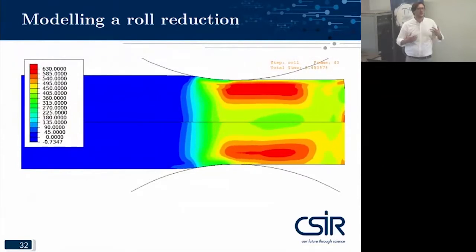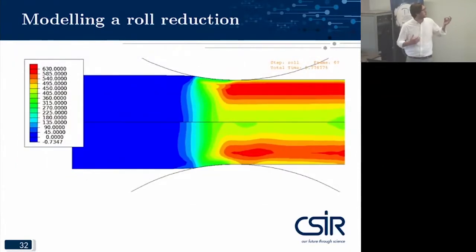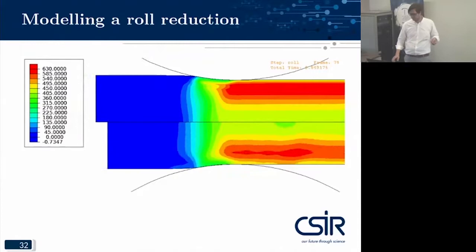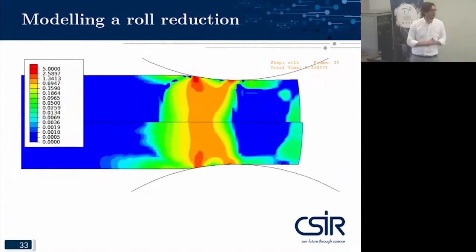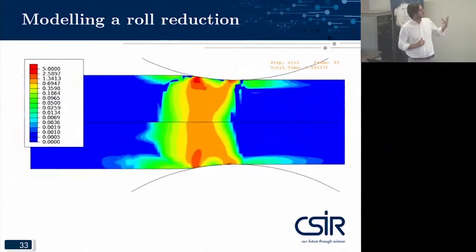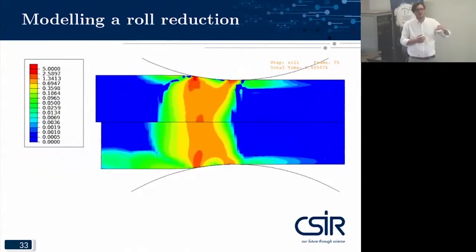And you can see again the importance of using small step sizes and accurate elements in terms of developing the steady state process. We also have deformation rate. So here you can see very clearly that it would be better to use a bilinear element at the bottom that has a fairly consistent prediction of what the deformation rates are compared to the higher order quadratic elements.